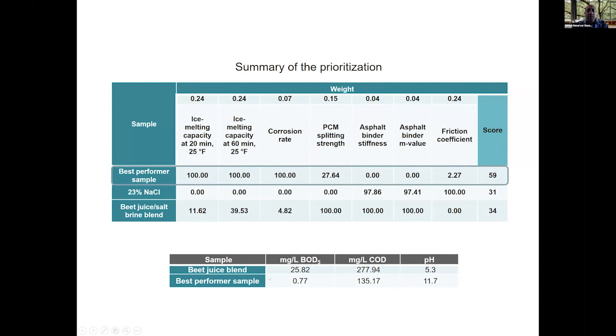You can see compared to beet juice blend, which is commercially available and used by many DOTs, our deicer has much less biochemical oxygen demand, and also less COD, chemical oxygen demand, which here you can see also it has better performance. So we could get a green deicer which has better performance compared to sodium chloride deicer, and also commercial green deicers, and less impact on the environment.